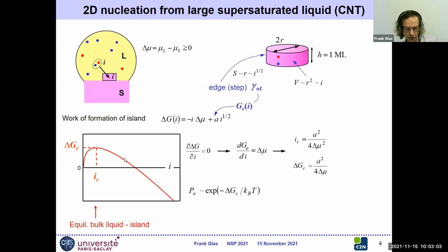So this gives the typical well-known nucleation curves. At the beginning, the positive term dominates, so it's not favorable to form the island. But because of fluctuation, we may reach this nucleation barrier at which, of course, the derivative of this work of formation with respect to size is equal to 0. And then after this, if we manage to overcome this barrier, then it's all benefit to add new pairs because the energy of the system will continuously decrease. So it's important to notice that this critical size, where we have this extremum of the work of formation, is defined by the zero of the derivative of the work of formation, which means that in this approach, the chemical potential is equal to the derivative of the edge energy with respect to the number of pairs. So these two terms are equal there.